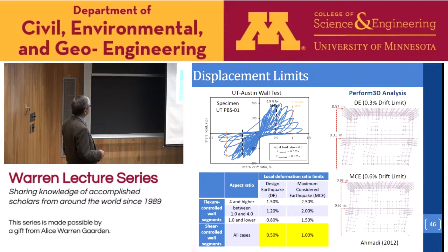This corresponds to the behavior of an individual pier. But if we translate into the story drift, we have to be more restrictive. So we end up with this displacement criteria for our design. This is for the design earthquake. We use a drift ratio of about 0.3% as the limit. For the maximum considered earthquake, we use 0.6% as the drift limit.